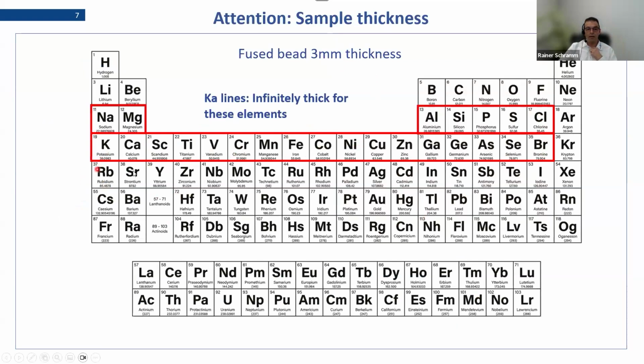If the atomic number is higher, you will see, like for strontium here, that the K-alpha line is really varying with the thickness of the bead. So you get a much bigger spread of your points in calibration if you would use the K-alpha line. If you then instead use the L line, you will see that you come back to the same performance as these mentioned elements. So that's the rule. Up to bromine, you can use the K lines, and then from rubidium on, you have to use the L lines to be always on the safe side that the total mass of the bead is not counting.